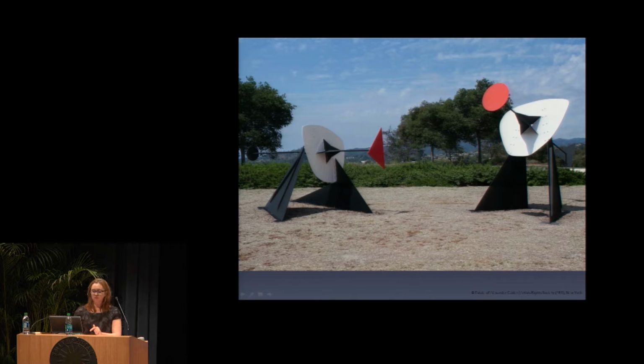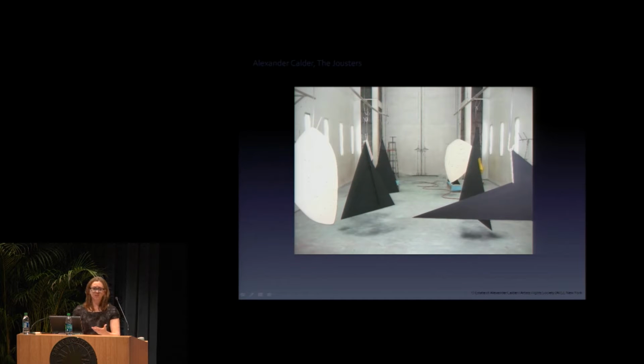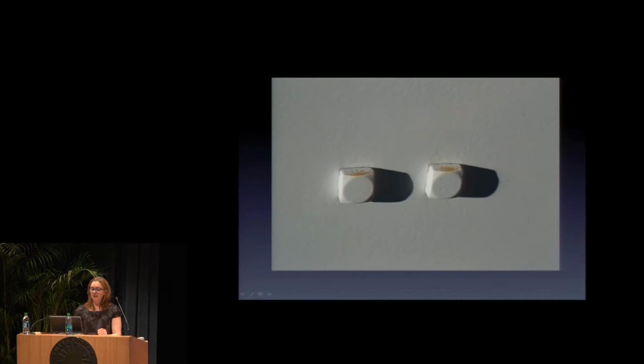When we repainted our Calder jousters recently, it was contracted work, and the painters used a chemical stripper, cleaned with acetone, and then reprimed and repainted. And unfortunately, it's a complicated process, lots of different parts and components bolted together. It's really hard to get a good, secure paint layer. And already, after 6 months, we're starting to see some rust. It wasn't just on the bolts, but on the plates as well. And we've talked to a lot of different paint chemists and manufacturers, and it kind of boils down to surface preparation and that the surface wasn't fully cleaned. And had we used carbon dioxide blasting, we probably would have gotten a better coat.